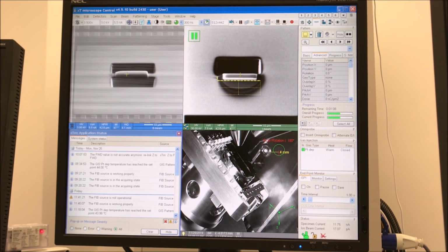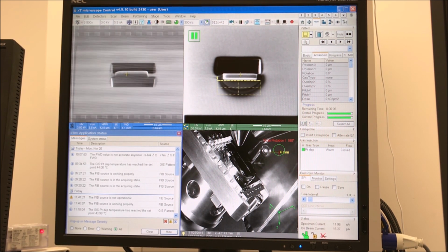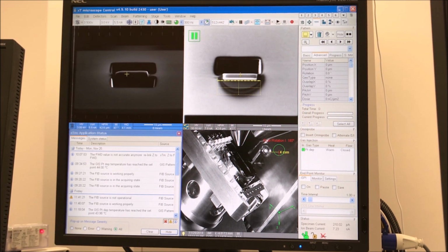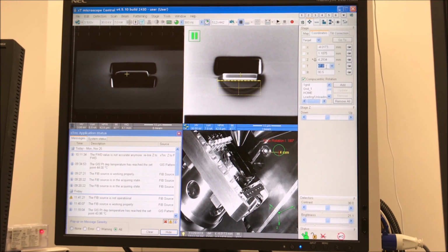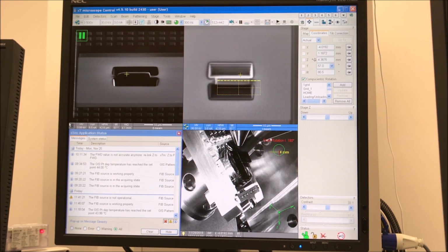So the reason for tilting plus or minus 5 degrees is it tapers the lamella from the top down and helps preserve the platinum. And again, remember, the goal of this sample is we're trying to look at that very, very near surface region of the material. So we really want to preserve the protection as much as we can. So I'm tilting back to 57.